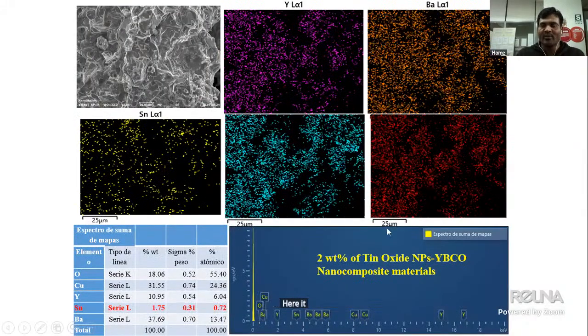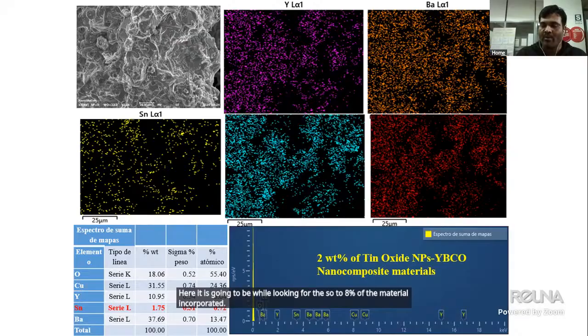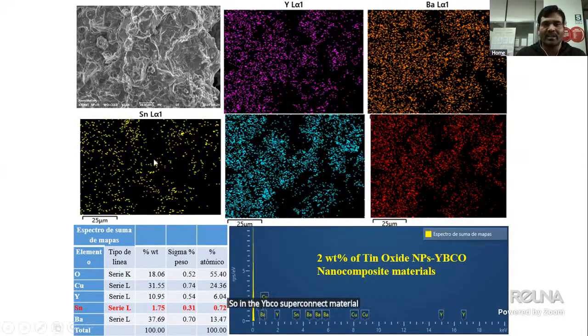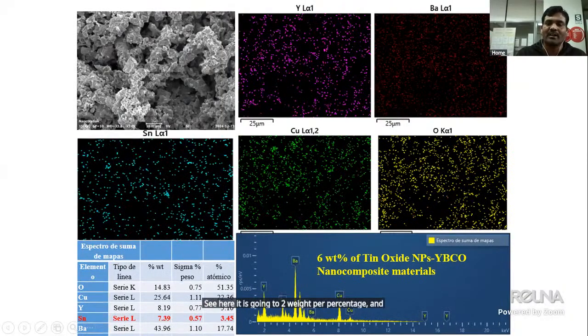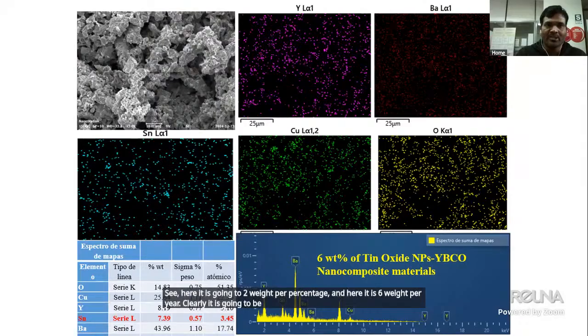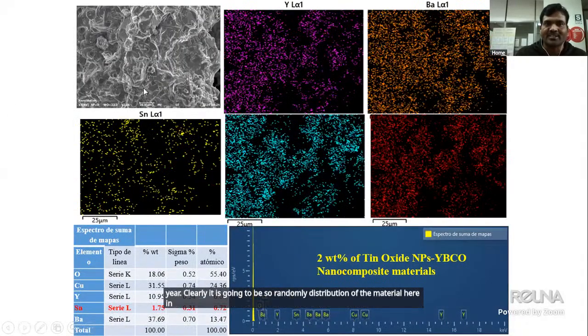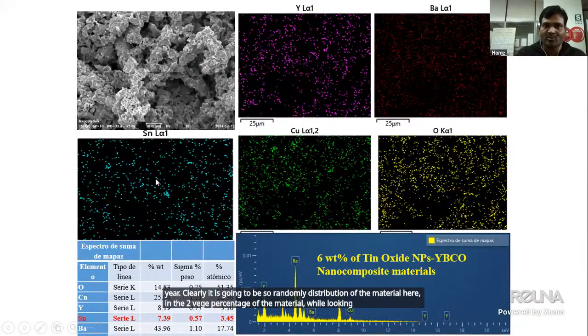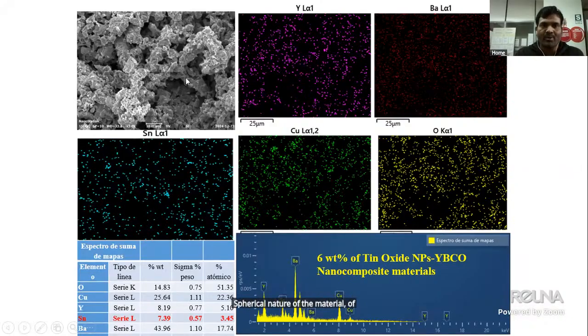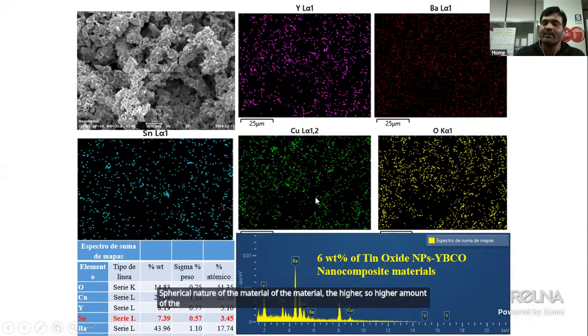Here, while looking at the 2 weight% of the material incorporated in the YBCO superconducting material, see the morphology of the material. Here it is 2 weight%, and here it is 6 weight%. Clearly it is a random distribution of the material in the 2 weight% sample. While looking at the 6 weight% sample, you can see clearly the spherical nature of the particles with the higher amount of tin oxide incorporated in the YBCO superconducting material. So we can easily notice the morphology of the material.